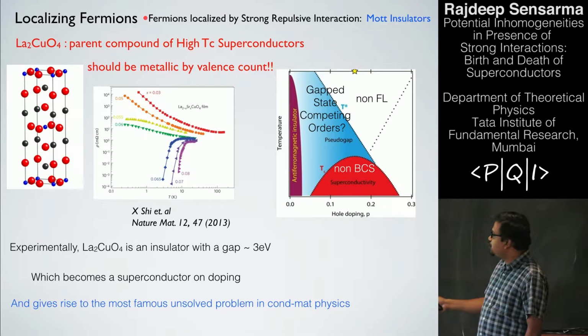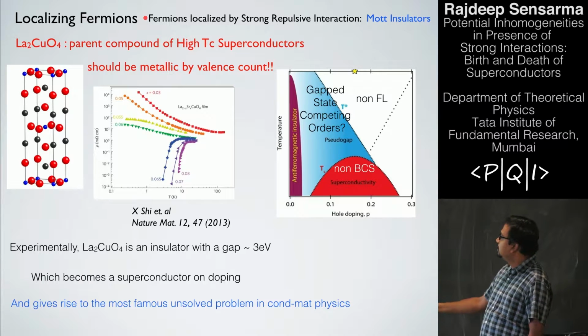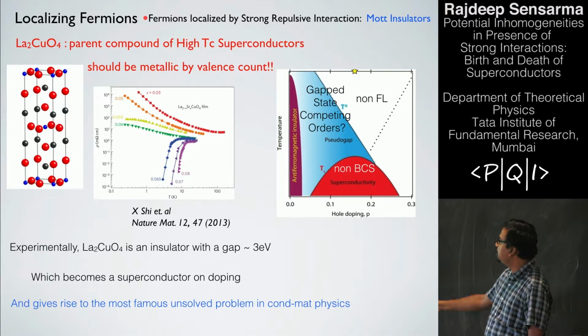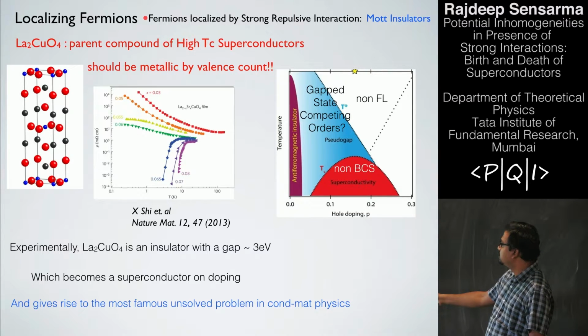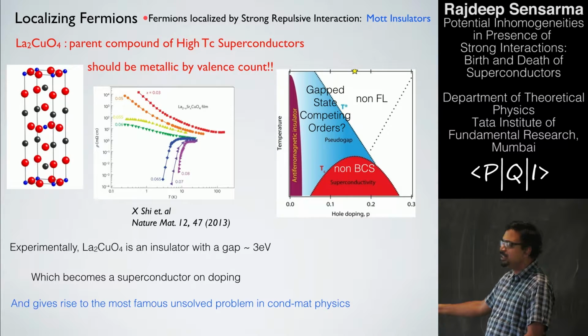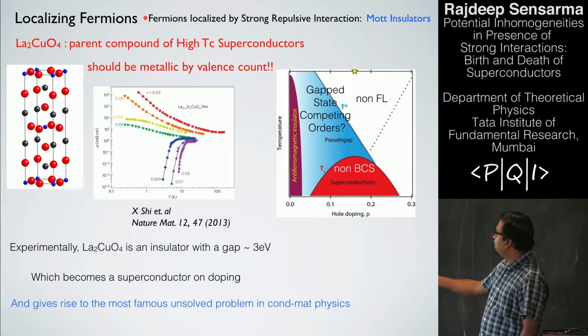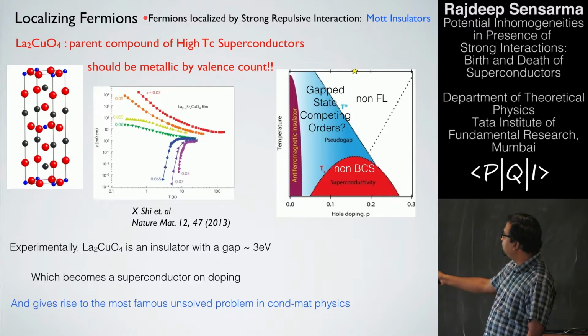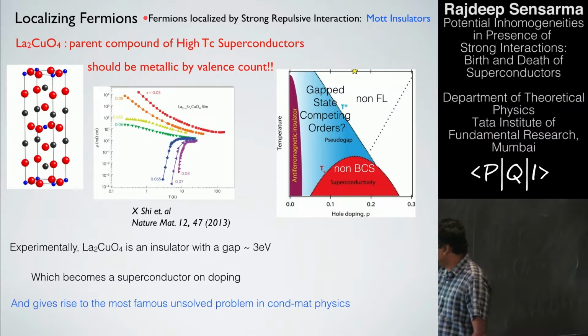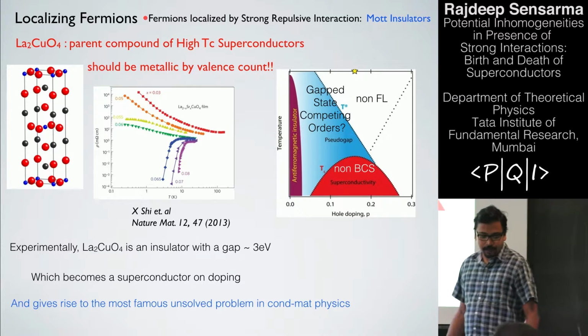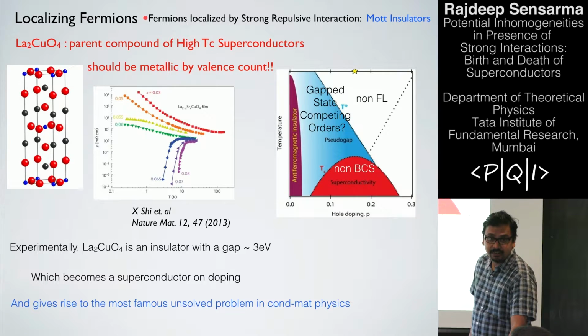However, if you now change the filling, then this shows a number of phases. There is an antiferromagnetic insulator at half filling, one particle per site. As you go away from that, you are giving less and less electrons. You get a superconducting state which shows very non-BCS type features. You get all sorts of states in the normal phase which we don't understand well. It's kind of the most famous unsolved problem in condensed matter physics.